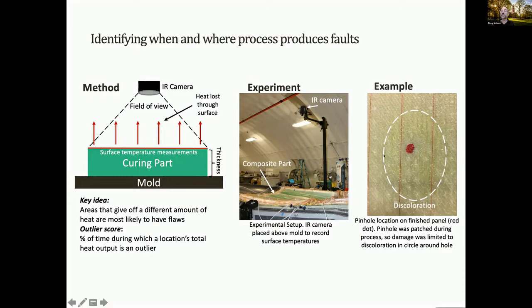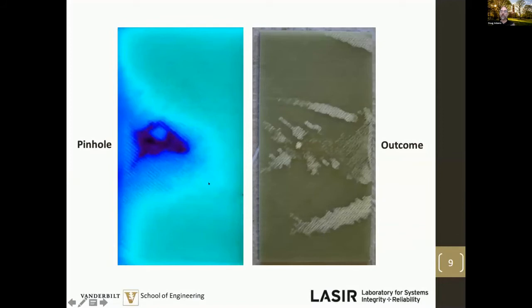And so, for instance, on the right here, you see that during one of these processes, we had a hole in the vacuum bag, and we were able to spot that and actually fix it so that we only saw small surface imperfections ultimately in the process. So for instance, this is actually what that looked like during the process. What we saw with our thermographic analysis was this pinhole that had occurred in the vacuum bag, and then here on the right is what it looked like after the process, after we had fixed the pinhole and allowed the process to continue.